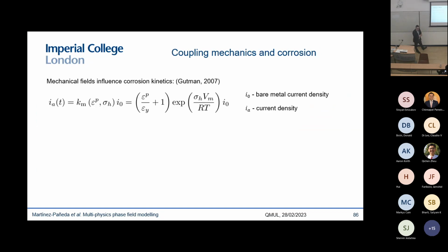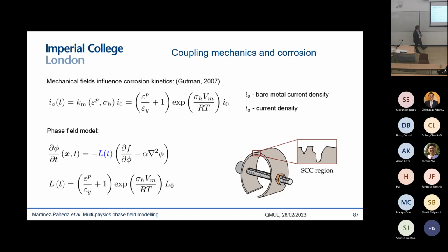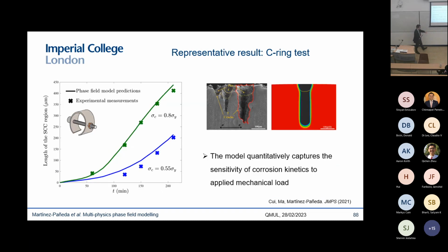And basically what we have done ourselves is to try to introduce more mechanics into these models. So we know that mechanical fields can enhance corrosion kinetics. This was discussed by Gutman already almost 20 years ago. And we can introduce that easily into the phase field because this mobility coefficient can be quantitatively related to the current density. So we can make our mobility coefficient dependent on mechanical fields. And then we can run some virtual experiments like this one to see whether we are able to capture the sensitivity to the mechanical fields.